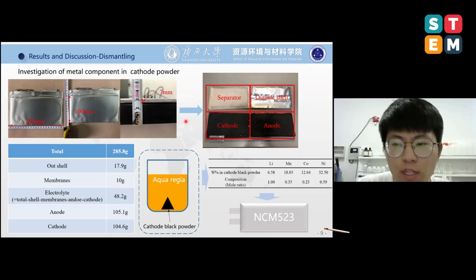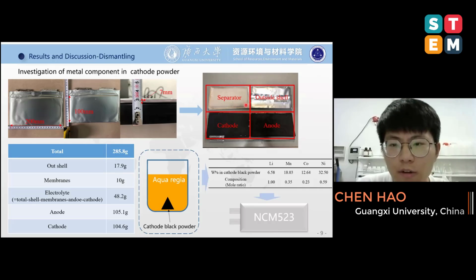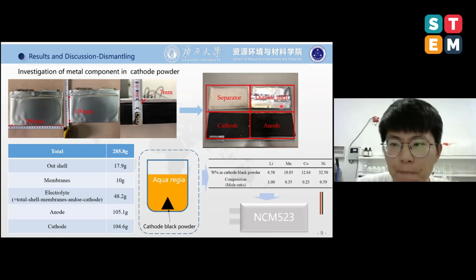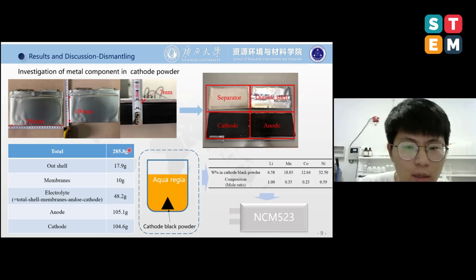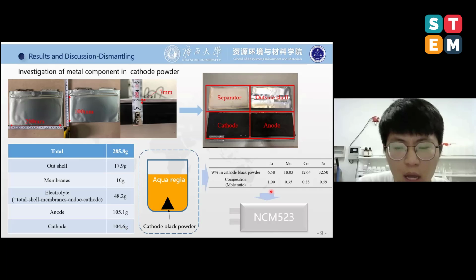After manual separation, we get the four parts. This is the separator. It is plastic. This is the outside shell. It is aluminum alloy. This is cathode material, and this is anode material, with the weight of every part. Total is about 300 grams, and the outside shell is 17.9 grams. Membrane is 10 grams. After calculating, we know the electrolyte is about 48.2 grams. Anode is about 105.1 grams. Cathode is about 104.6 grams.